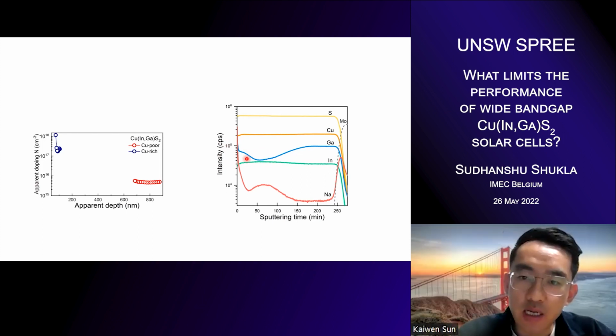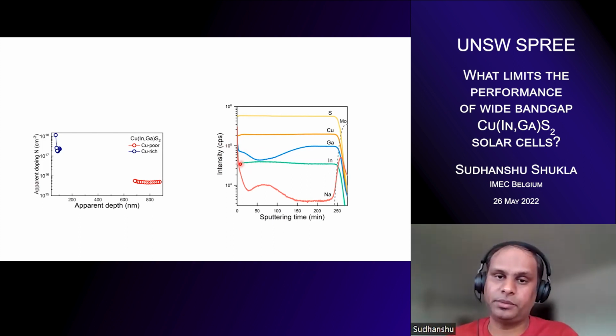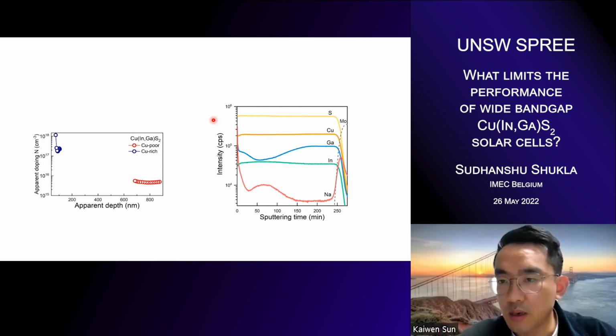But you don't see the indium segregation? That I don't see. At least experimentally, I don't see any indium segregation at the surface. Okay, great. Thank you. And I think that has to do with the diffusivities of indium and gallium within the copper-poor CIGS matrix. Okay. Thanks. Any other question?